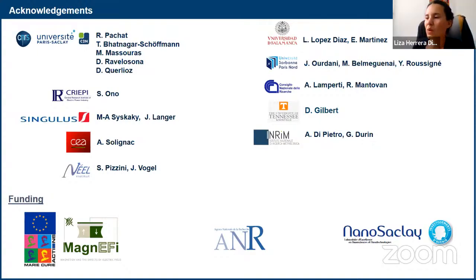Thank you. Yeah. So for the magnetic moment, yes, we have seen that the magnetic moment can decrease a lot with oxidation. With both the cobalt and the cobalt iron boron that I showed before, we measured it with SQUID, and we could see a decrease in the magnetic moment. At some point with our collaborators from NYU, we wanted to see if there was an exchange bias at low temperatures because of cobalt oxide, but we couldn't see it. As I said before, there was not a huge oxidation, but we could definitely pick it up in the SQUID. So there is really a decrease which goes together with an oxidation.